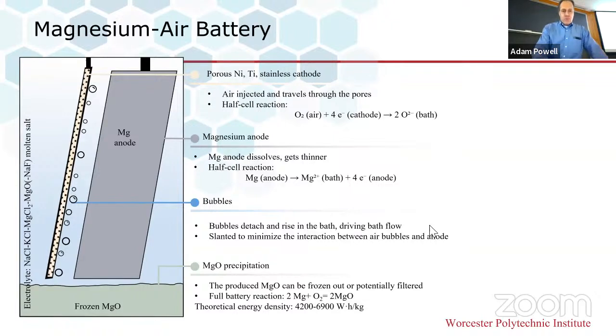So the way it works, as I mentioned, we inject air into a porous cathode. It can be made of nickel, titanium, or stainless steel. And we found that for many hours in air with a molten salt, nickel is just fine. It doesn't oxidize, let alone dissolve. So it's pretty remarkable. And as I mentioned, it generates a voltage through these combined reactions, oxygen to O2 minus, magnesium to Mg2 plus. And these two dissolve in from the anode and the cathode into the molten salt. So your overall reaction is just the oxidation of magnesium to MgO.